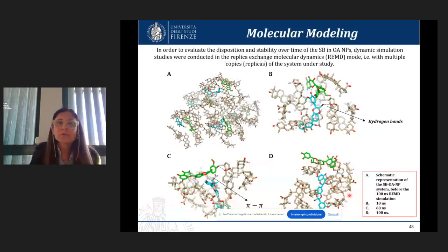In this case, we also performed a molecular modeling study to evidence the interaction between silibinin inside the nanoparticles and oleanolic acid. The interactions are due to hydrogen bonds, pi-pi interaction, but also van der Waals interaction. The molecular modeling proved the stability of the system, and also showed a low release of silibinin from the nanoparticles, as also evidenced by our in vitro release study.